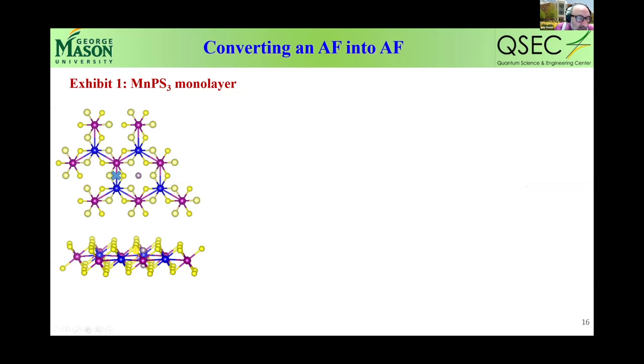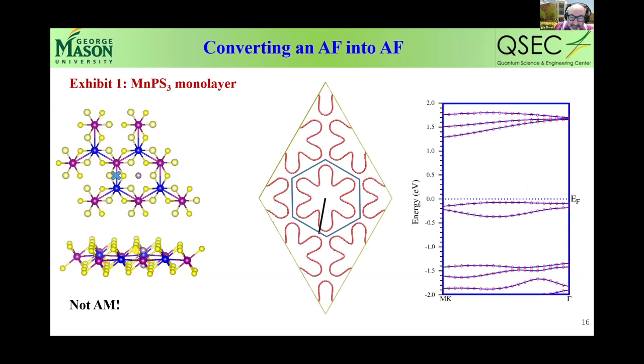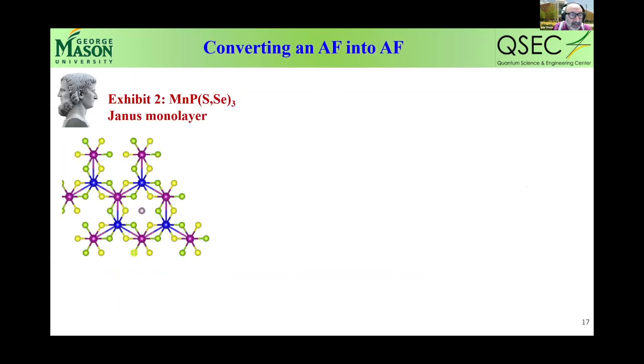So you can see that there are two manganese atoms here, magenta and blue, and there is an inversion symmetry between them. Now, importantly, there are other symmetry operations that map one onto the other, but among them, there is also inversion. That's enough to make it a normal spin-degenerate antiferromagnet. And you can do the calculation. The calculation, of course, confirms that, because symmetry never lies.